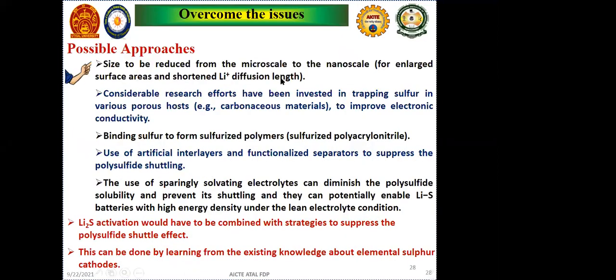Like we can reduce the size of Li2S, so that our surface area will be enhanced, and lithium diffusion will also easily happen, so that our charge transfer will also be faster, and the distance will be reduced considerably. We can also generate Li2S cathode with a different material like a porous host, or we can add some carbon like vulcanized carbon, or some sp2 carbon to improve the electronic conductivity and reduce the sulfur trapping in the Li2S.